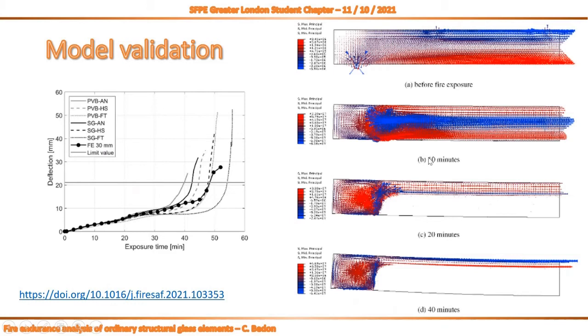The reason is just related to the degradation of Young modulus with temperature, something that we can easily justify in the form of bending stiffness modification as a function of temperature, so exposure time, and for sure we can associate to a transition, migration of stress peaks to other regions of our beam. And this is very simple to see because here we have the mid-span section. So it happens that after 10 minutes, we are more or less at 5 millimeters of deflection. The effects of fire can be still disregarded, and you can see a very small layer in the bottom, which is white, so representing glass material which is no more able to carry on the mechanical loads.